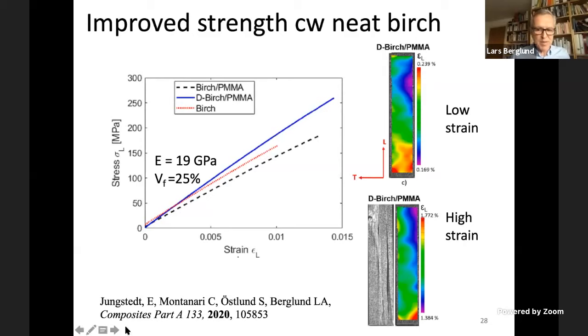He gets strength values of 250 megapascal. He gets a modulus of 20 gigapascal, although he only has 25% of wood in his composite. And his properties are significantly better than both neat birch and birch that is not delignified. It's interesting to look at the strain fields that he measured. At low strain, we have some inhomogeneity here where we have higher stress. This is the larger strain, and it's related, of course, also to higher stress. Here is at high strain, and there you see that the fracture initiates in this high strain region, and then we have very dramatic failure of our material.